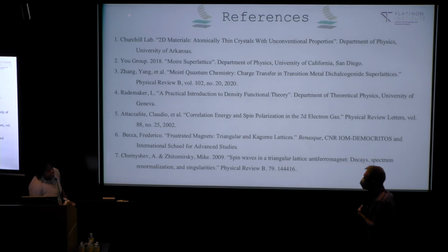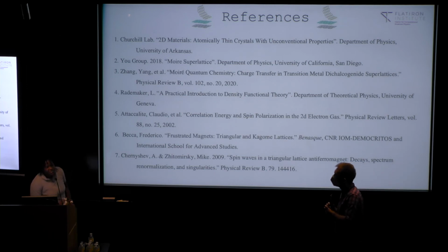I know a popular one is MoS2 right now. The difference is that in the model we're studying, the heterobilayer, there are 2 different materials. With graphene, it's the same material stacked on top of each other, so to have the Moiré potential emerge, you have to stack them and then twist them to a specific angle to create the lattice mismatch. This is an easier way to have that Moiré potential emerge.